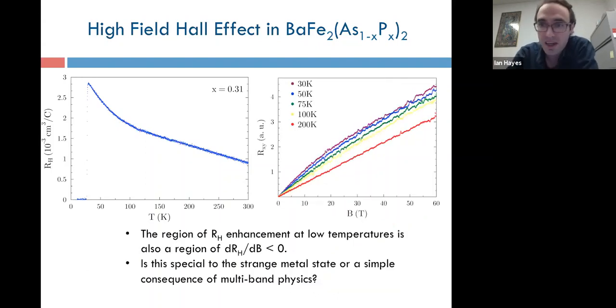So this has the makings of an interesting correlation between a particular field dependence, a decreasing RH with field, and the strange metal behavior in the temperature dependence, increasing as you go toward lower temperatures. And I will show you, based on where this particular field dependence lives in the phase diagram, that it's very unlikely to be a simple band structure effect. Probably it is related to whatever scattering, whatever interactions are responsible for superconductivity.